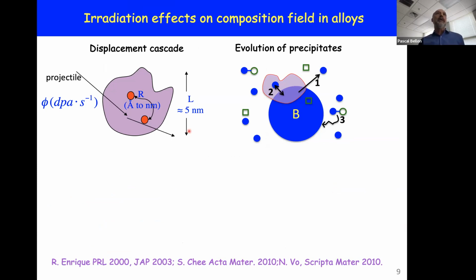picking up from this brief description of radiation damage in alloys, imagine that here we have an incoming projectile that has created this displacement cascade extending over a few nanometers, lasting a picosecond or two. In that displacement cascade, atoms, as I mentioned, will be forced to relocate from their initial position to a nearby location. The relocation distance R varies from an angstrom to a nanometer roughly. And if I have a precipitate that's, for simplicity, assumed here to be a pure B or pure solute precipitate, some of these relocation events, here as process one, some of these solute atoms would be relocated into the matrix. So it's going to contribute to the dissolution of the precipitate.